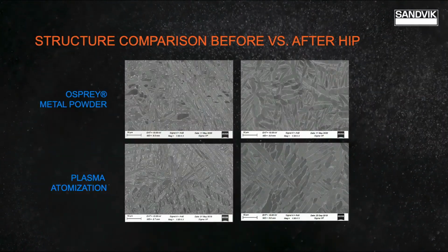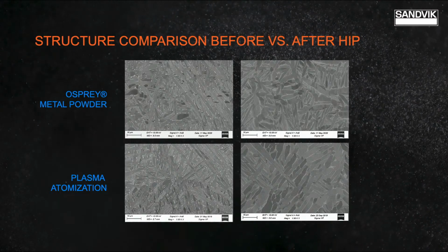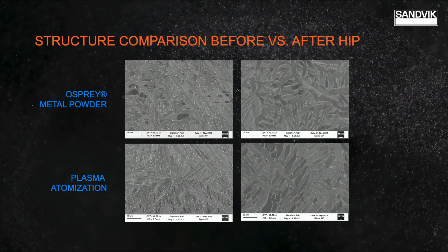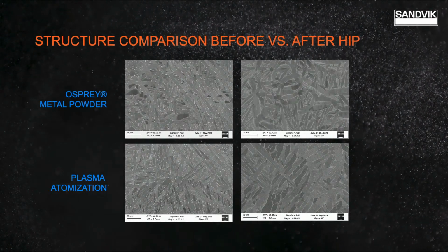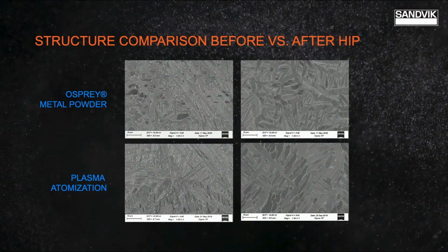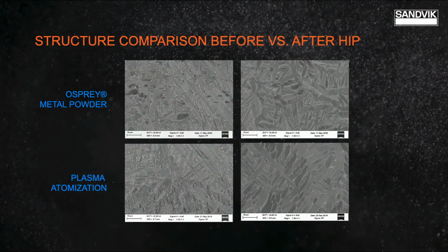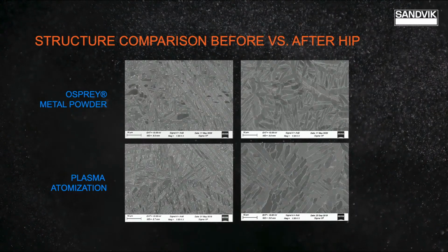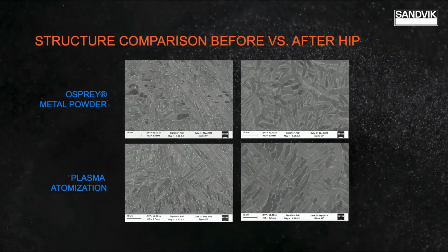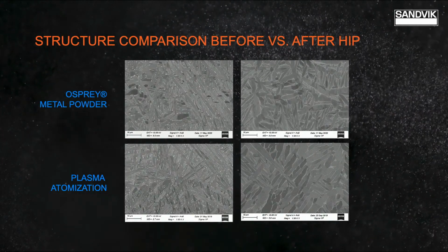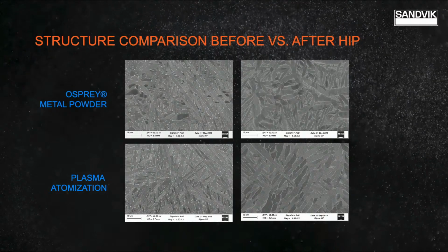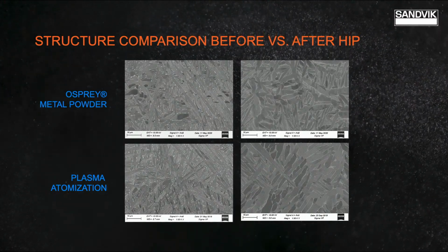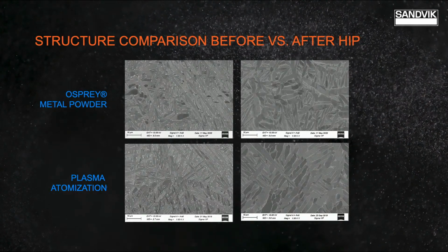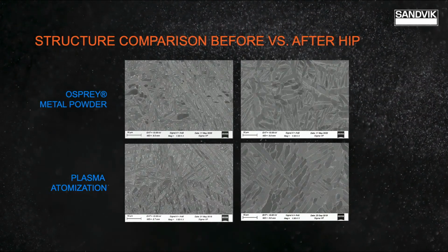Well, Harold, you're very right. That competence would be very valuable for us. And the process of comparison of material data starts with the microstructure. So as you can see on the screen, differences in microstructures after printing will usually indicate whether we have a stable process or not. And from there, we can take further actions to mitigate these observations. Other improvements can be done, such as stress relief treatments or hot isostatic pressing. And this is when you have more defects, such as porosity. So Harold, to be able to provide our customers and partners with the best set of data, we must go to these 2 analyses.